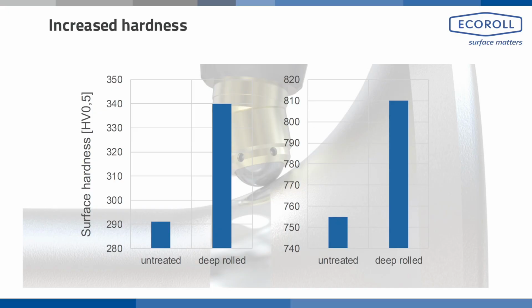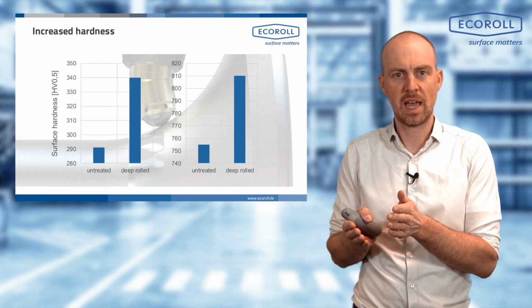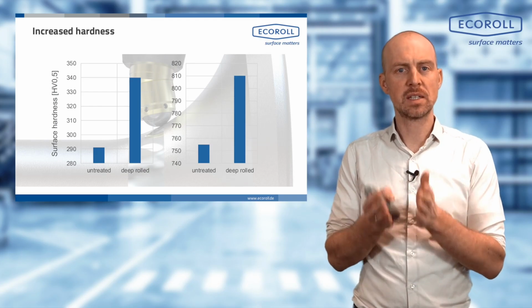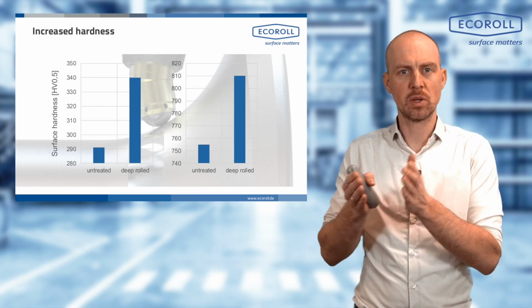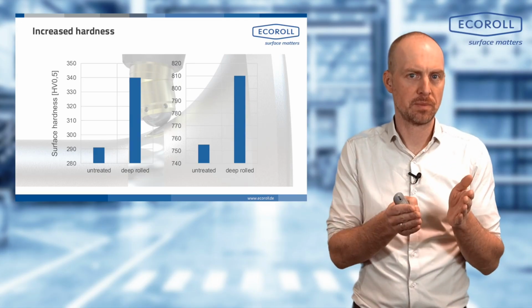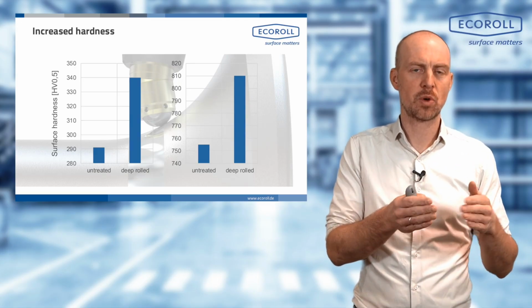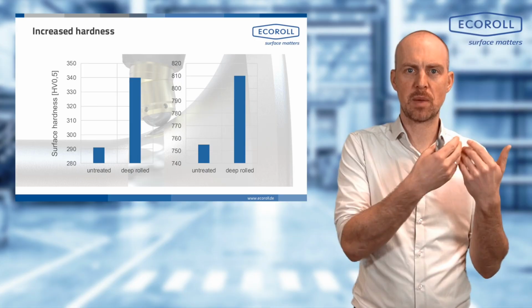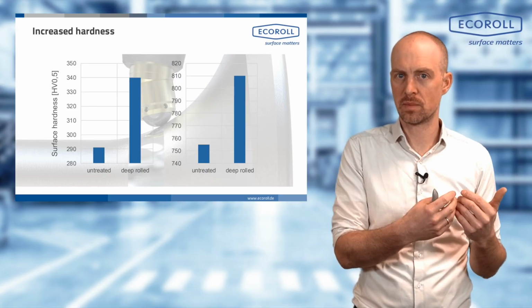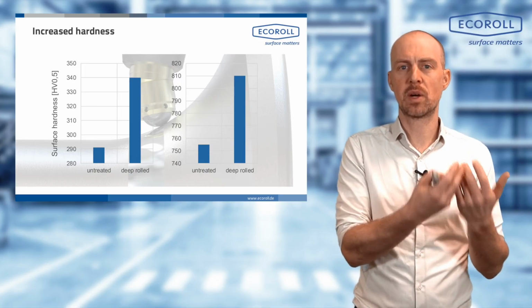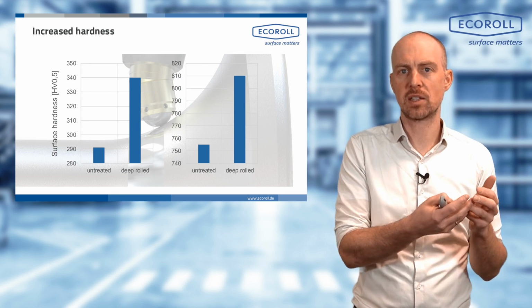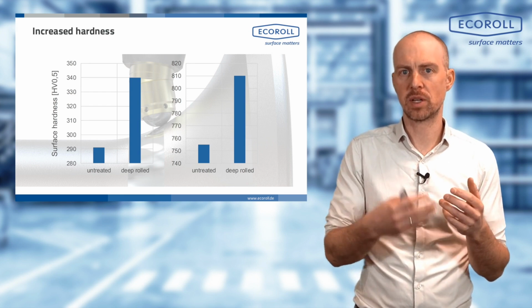And I can now, of course, use this effect to strengthen my component. And I can also use it to significantly increase the service life of my component. So I don't necessarily have to, and here's the point I want to make, I don't necessarily have to harden my component to increase its service life. I could carry out this process, this deep rolling, simply after my machining on the same machine, and thus introduce residual compressive stress, introduce work hardening, and so increase the service life of my component.